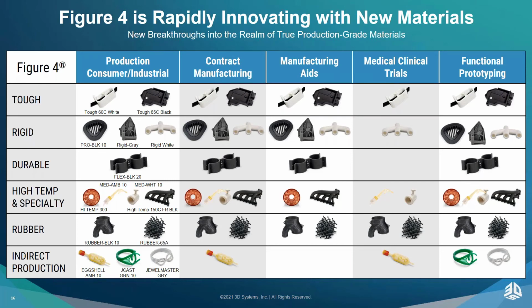And one of the nice things about these type materials, because of the color stability, because the tensile modulus is really good, I can just take and put holes and screw these parts in. And so elongation is never a part of that application. It's a static part. There's no load on those parts. And what I'm really relying on is the HDT of the part and the color stability of the part, that those are not going to change over time. And so I can look at the different properties and use that.